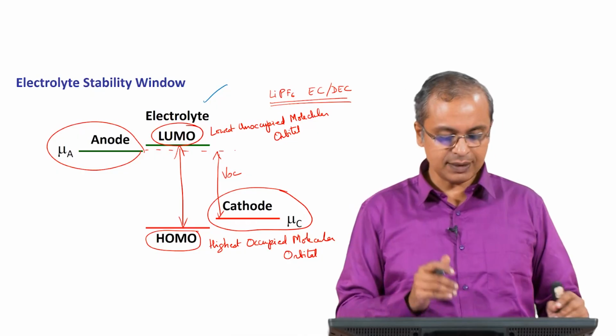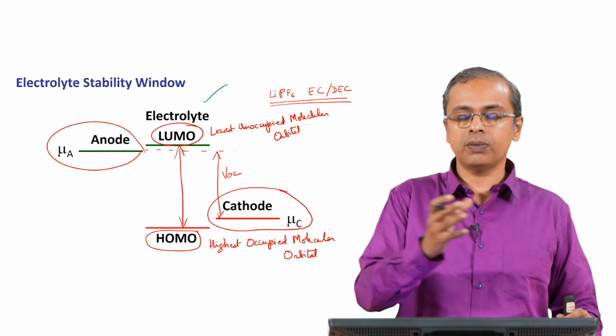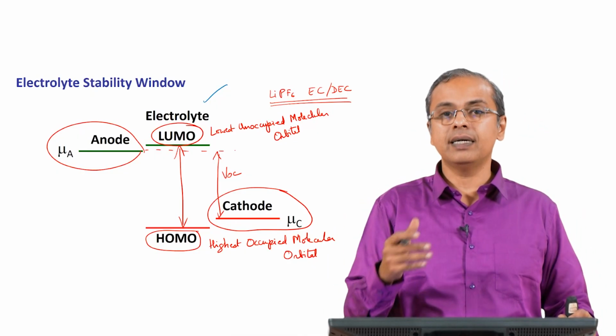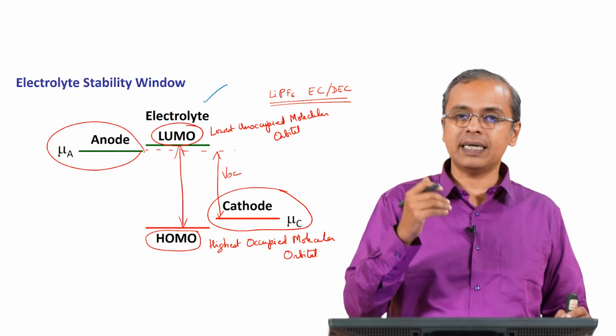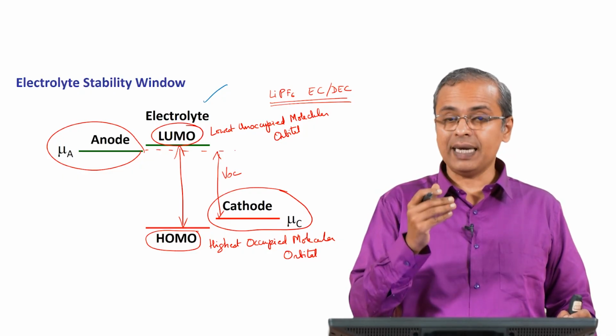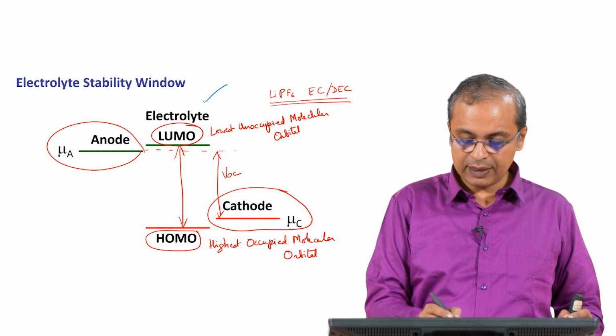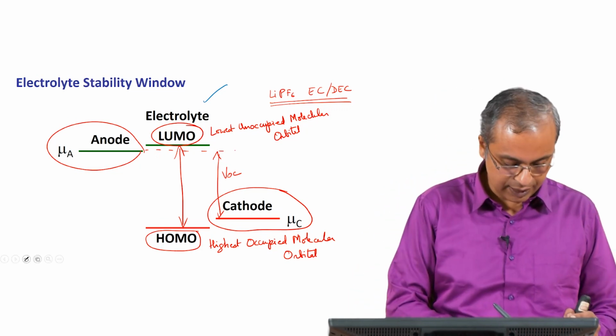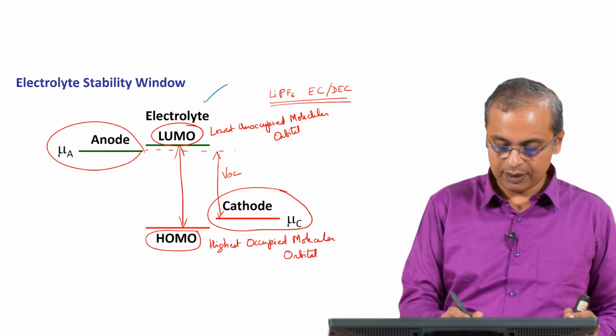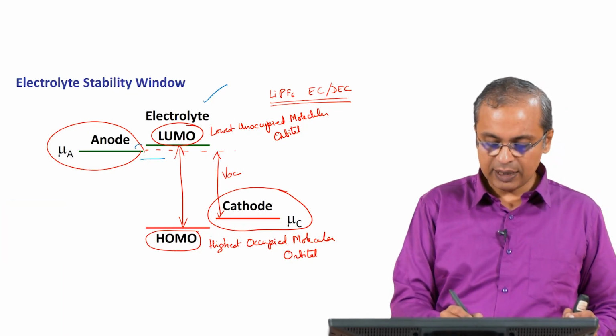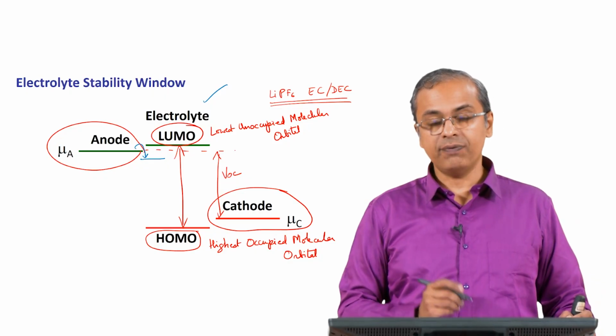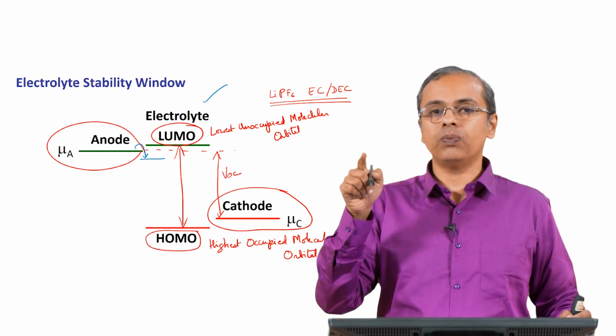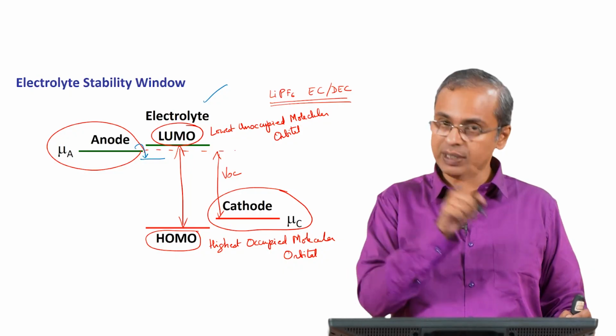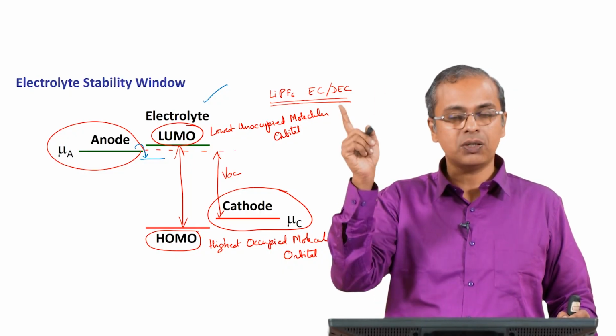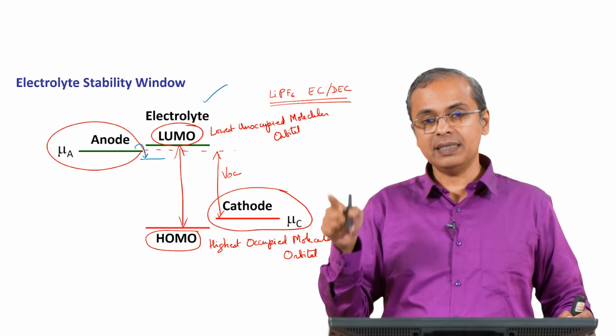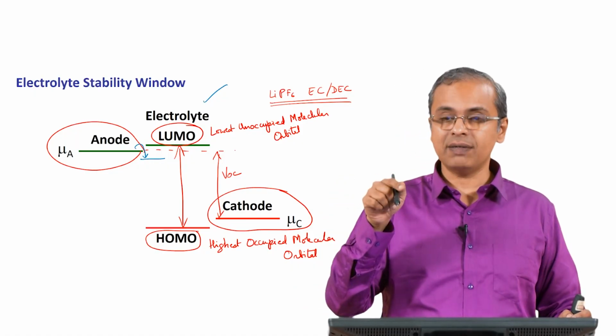Why is this the case? It is because at the anode during the normal discharge process, when you use the battery, the anode material is getting oxidized, right. So, it is releasing electrons. Now, if the LUMO, the lowest unoccupied molecular orbital of the electrolyte, were to be lower, let us say it were here, then this electron can directly go to the LUMO itself, in which case the anode is actually reacting with the electrolyte, it is reducing the electrolyte. The anode is getting oxidized, but instead of releasing the electron to the external circuit, it is actually releasing the electron to the electrolyte, and the electrolyte itself is getting reduced.